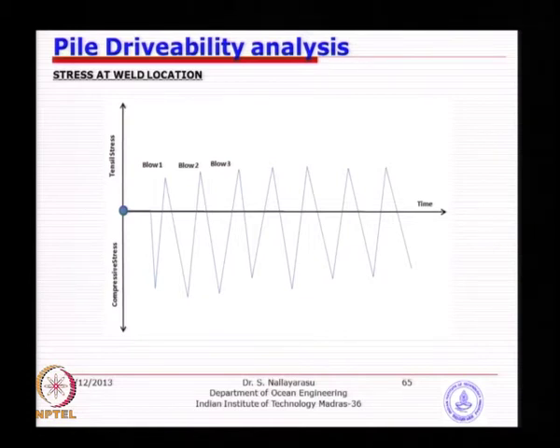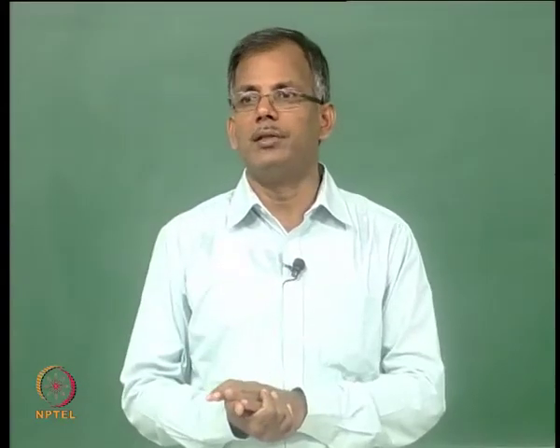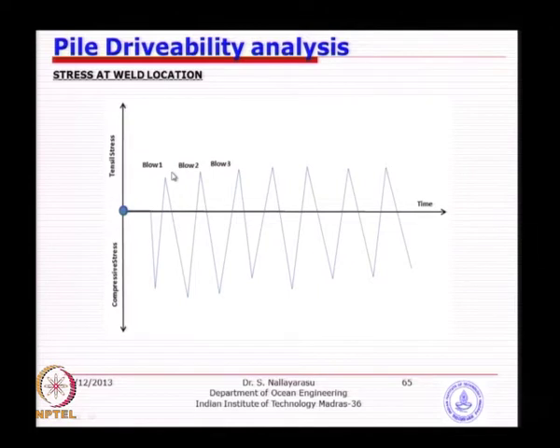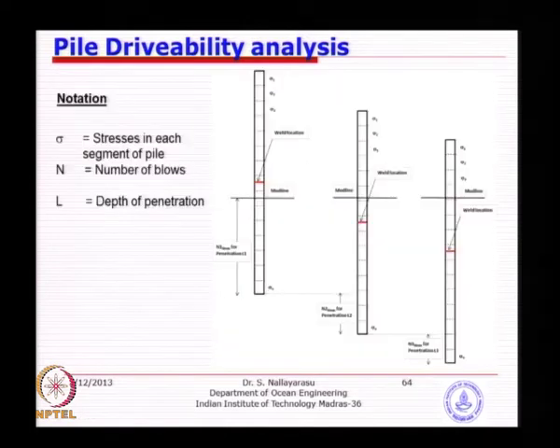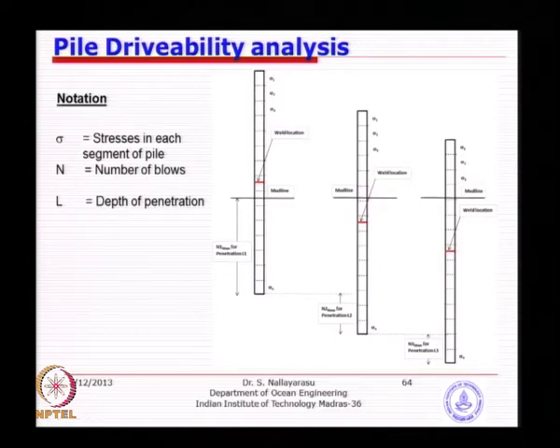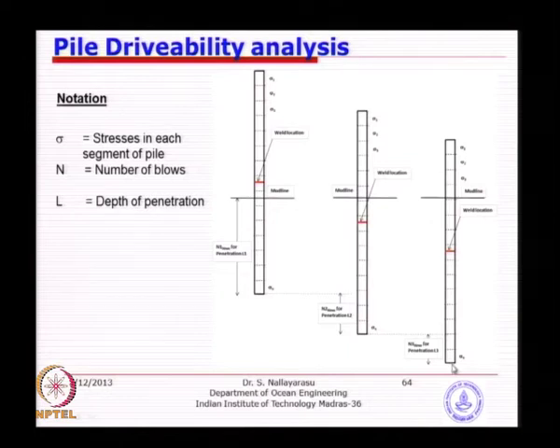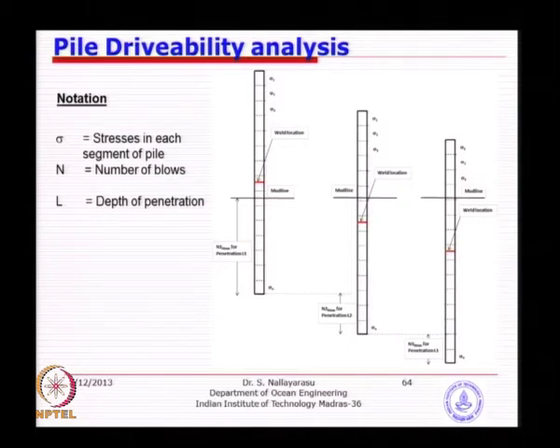One of the fatigue criteria is that the load must be cyclic — it has to change from positive to negative, or there should be a variation in stresses. In this case, there is a compressive stress, then a tensile stress at slightly different time intervals because the stress wave travels through and returns back. Unless it is hard driving, the reflected stresses will be very small. At the end of driving, trying to reach final penetration, the tensile stresses may be higher.